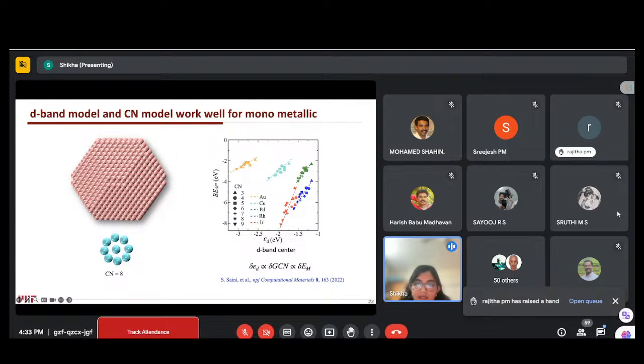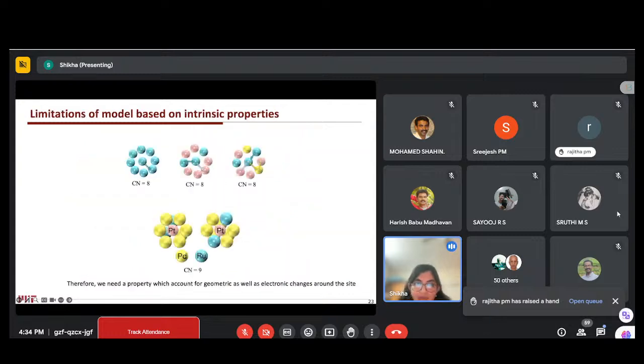So the binding energy will be higher if the d states are away from the Fermi level. So that way, for the monometallic system, we understand them well. If we know where our D-band center is and what the coordination number is, then by given those values, we can predict how reactive our surface would be. But when we go to the alloy system, what will happen?